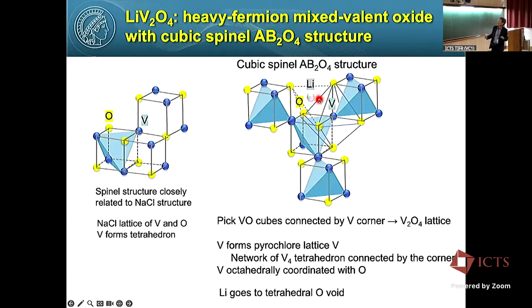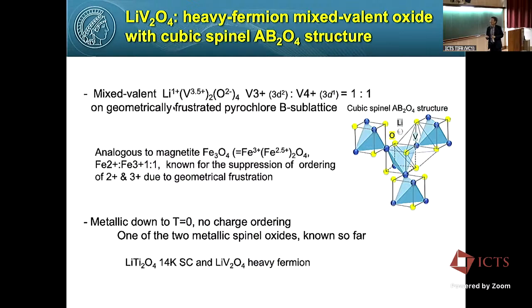And lithium is located here, surrounded by 4 oxygen, tetrahedral type. And you see vanadium here is coordinated with 6 oxygen, so they are in an octahedron, octahedrally coordinated. And just counting the valence, lithium is 1 plus, oxygen 2 minus. Because of an odd number here, vanadium has a half-integer valence, 3.5 plus.